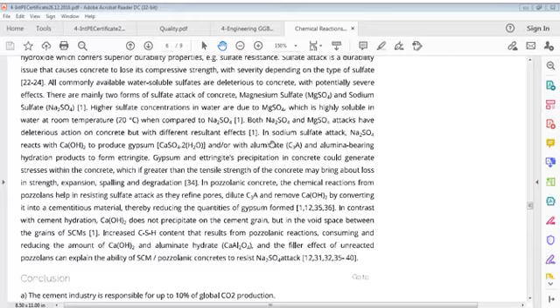In sodium sulfate attack, Na2SO4 reacts with Ca(OH)2 to produce gypsum, CaSO4.2H2O, and or with aluminate C3A and alumina-bearing hydration products to form ettringite. Gypsum and ettringite precipitation in concrete could generate stresses within concrete, which, if greater than the tensile strength of concrete, may bring about loss in strength, expansion, spalling, and degradation.